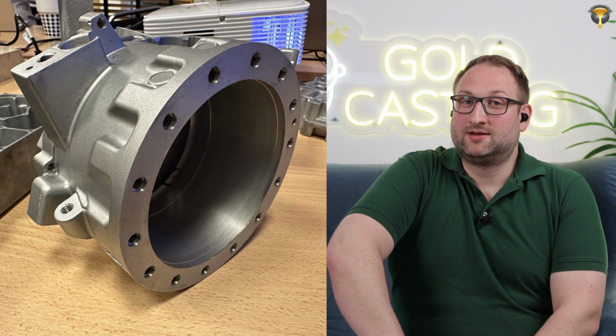And the extreme of that, what you can do is, what about helium tightness? Because we're now seeing that with the EU F-gas ban, that the standard R134A compressors have to be phased out for new platforms. What do? If you want to cool a battery and also the interior, you need something way more efficient. Otherwise, it goes towards your consumption and therefore your reach and range. Yeah, a CO2 compressor can just plug in basically there in that system. It uses the same setup. You can heat and cool in the same circuit, and now you have triple the efficiency. But you're not operating at 15 bars, you're operating at 150 bars or 160 or 180 bars.